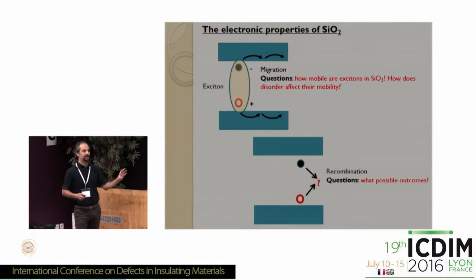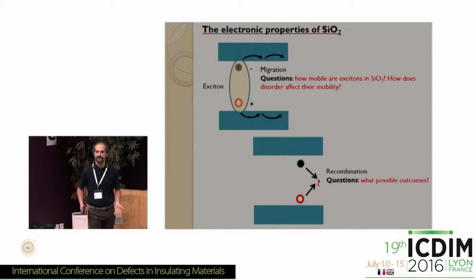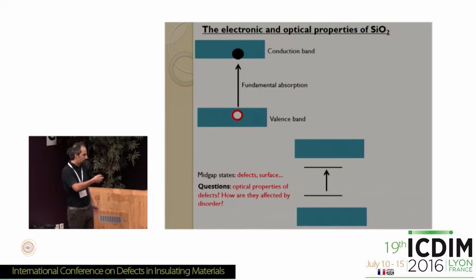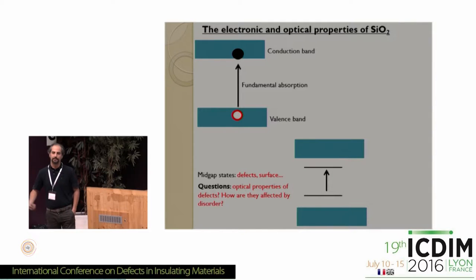And then, after some movement, the excitons will eventually recombine, and they can do that radiatively, with exciton luminescence, or non-radiatively, in which case, for instance, you may have the generation of point defects. So the other question here is, what are the possible outcomes of this recombination? Of course, things change if the solid is not ideal and you have defects, because this is a defect conference. Everybody knows that defects introduce some mid-gap states, which give rise to new optical properties because you will have absorption and luminescence between these states.